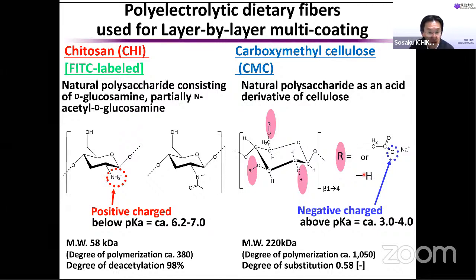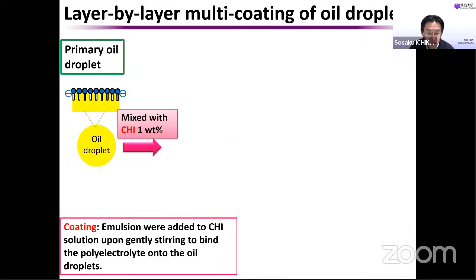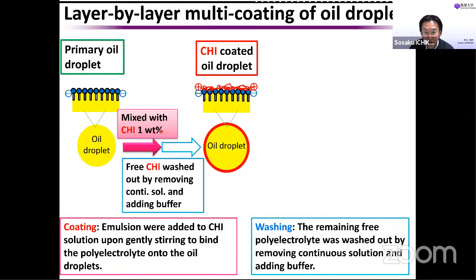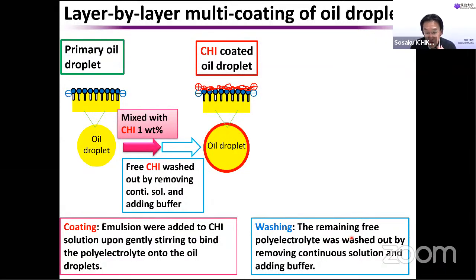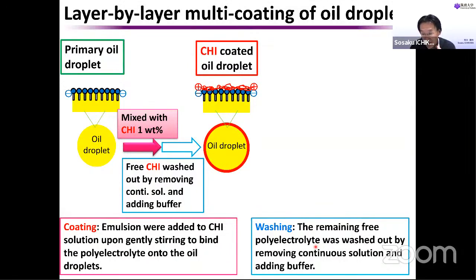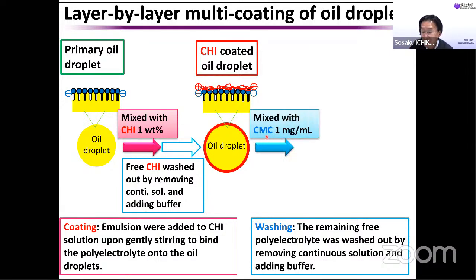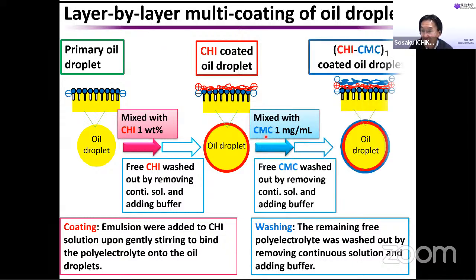Firstly, we mixed with the chitosan. CHI means the chitosan. Then we get the chitosan layer on the oil droplet. Then we wash out the remaining free polyelectrolyte, chitosan, by removing the continuous phase solution and replacing it with buffer without chitosan. After that, we mix with carboxymethyl cellulose, CMC, then we get the CMC coated oil droplet. At this stage, there are two layers on the oil droplet.